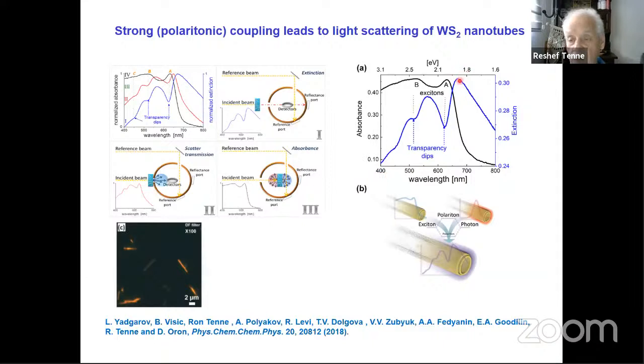a big shift in the spectrum compared to the A and B excitons, and this shift was explicitly explained via polariton. Polariton is a hybridization of a cavity mode that goes in the nanotubes like a fiber, enclave the optical mode into the nanotube, and then interacts with the excitons and hybridizes with the exciton, forms strong coupling and polariton. I won't go into the details because I don't have time.